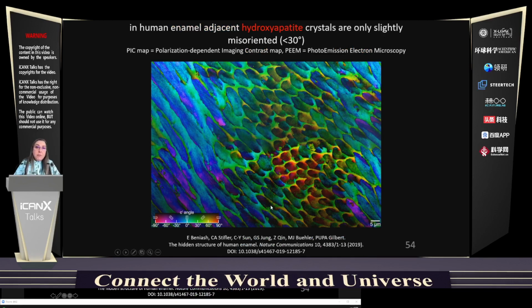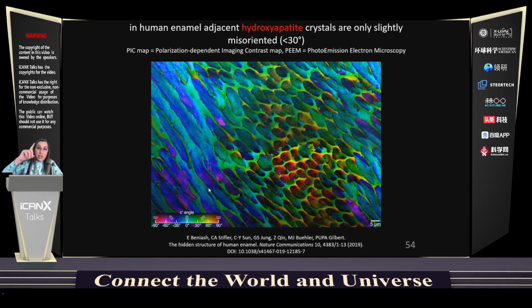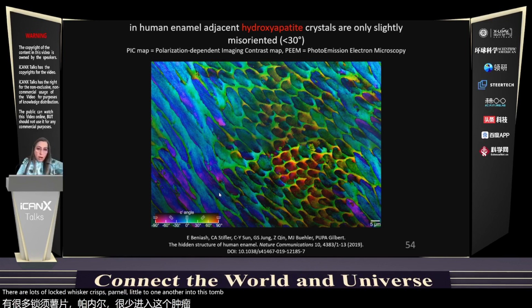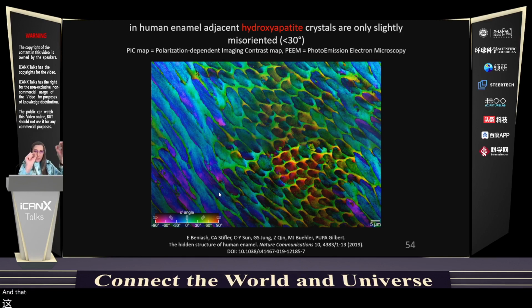This is from human enamel in our teeth. And you can see these structures called the rods that are actually gradually changing color in a PIC map, which means gradually changing orientation. And so you see that within this one rod, there are lots and lots of whisker crystals parallel to one another into these tubes called rods. And they are 50 nanometer wide and many, many microns long.